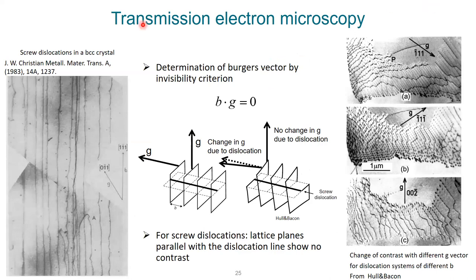Here I show a typical example of a TEM measurement from the literature. This example from a publication shows a lot of straight lines, which are all screw dislocations in a BCC crystal. Another example from the book of Hull and Bacon shows an additional interesting capability of TEM: to also determine the Burgers vector of the dislocation. That is done by selecting appropriately the diffraction vector G. By changing the diffraction vector, your TEM image will change.